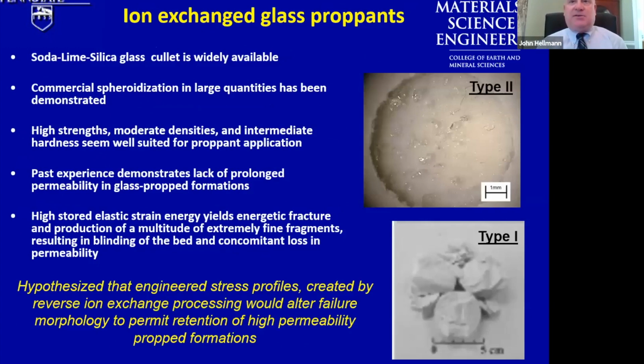Glasses have been considered for use as proppants for decades. Glass particles that are highly spherical can be manufactured in very high strength form using flame spheroidization processing. They're readily available, in the kinds of quantities that would be commensurate with use as hydrofracturing additions. However, they don't work. And they don't work because they're such high strength.